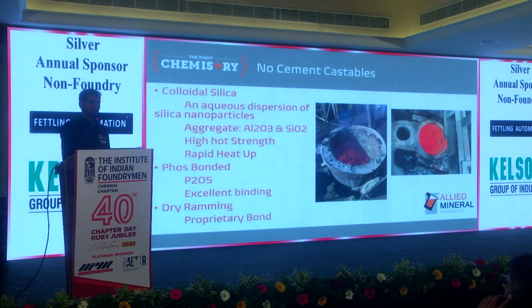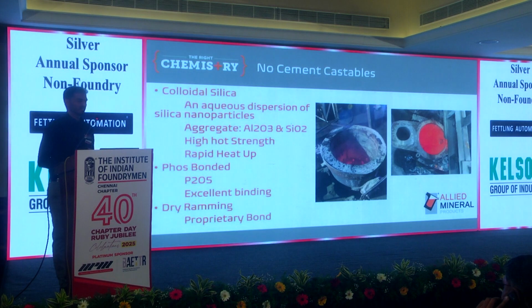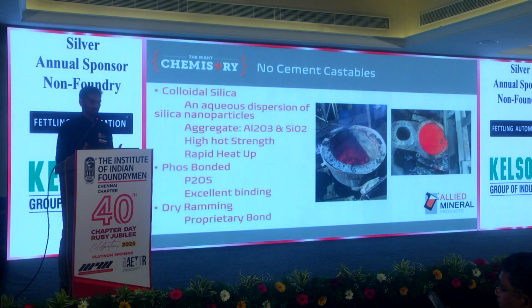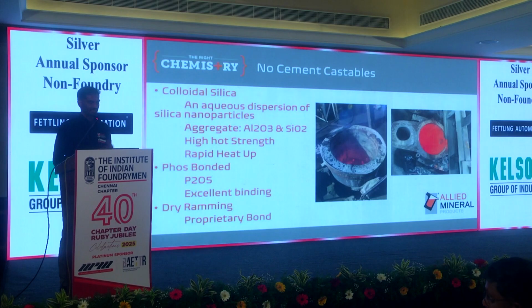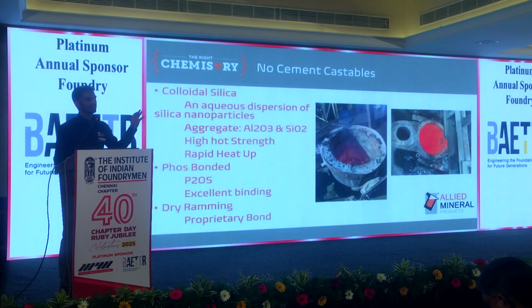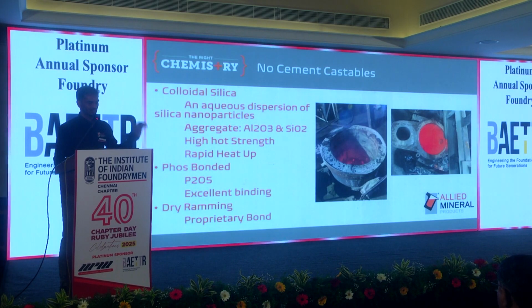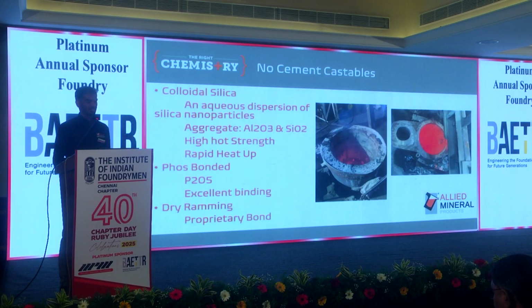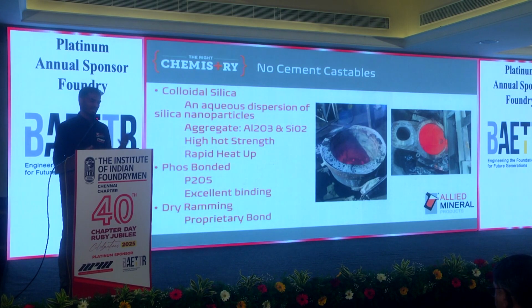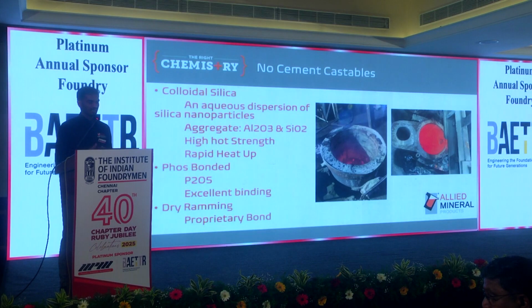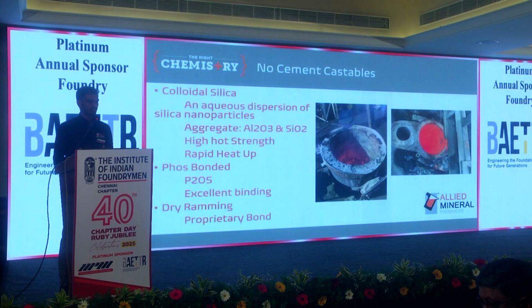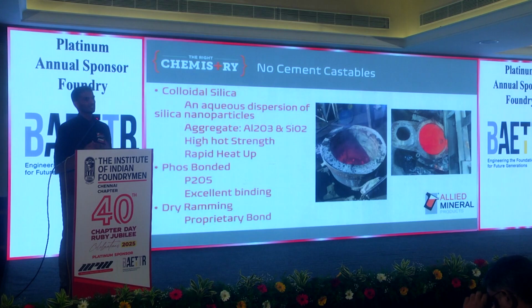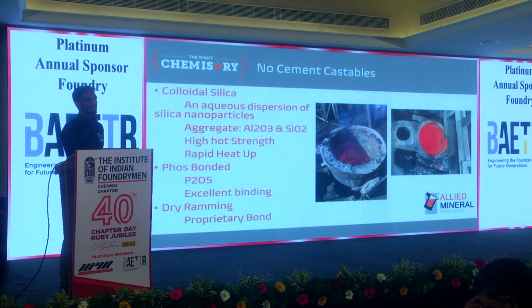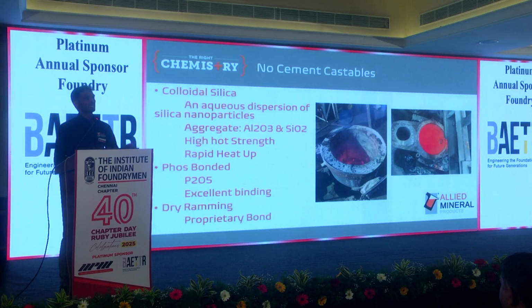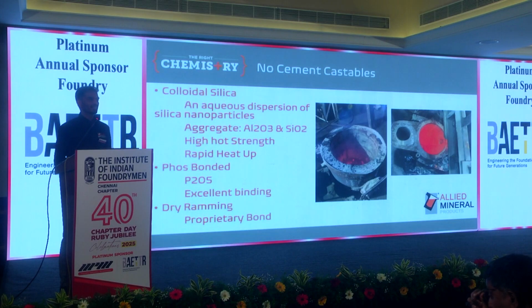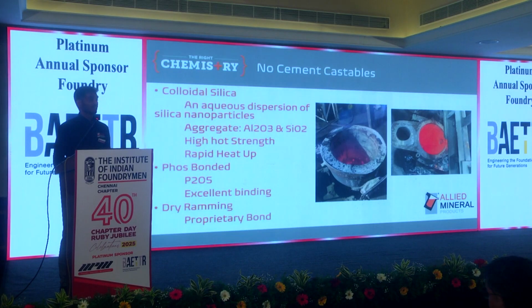So when I talk about no cement castable, this is something we started to produce and push in the market as a colloidal silica based product. As I said earlier, there is no CaO content or any other binding in the system. We have a binding agent called colloidal silica, so we add it along with the aggregate, mix it up and place it. The only advantage is, since it does not have any cement and water is not being added into the system, the heat up can be very rapid. So your downtime of ladles is very much minimized.